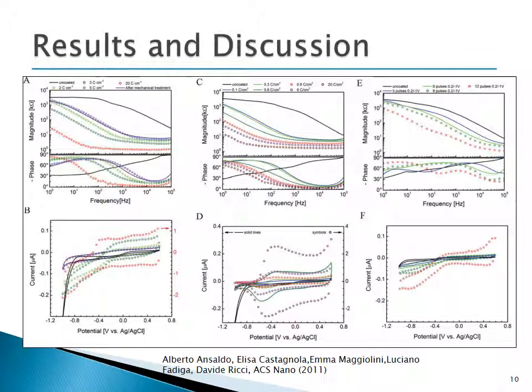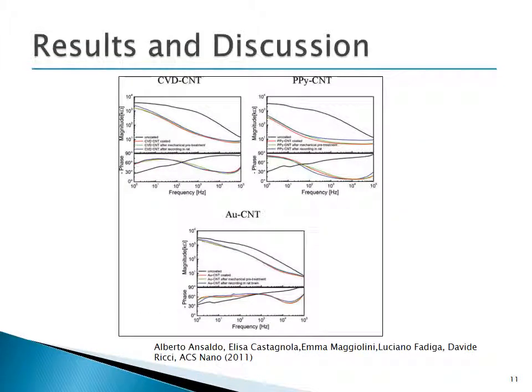Now the results. Here in these graphics, we can see that the black line corresponds to the uncoated electrode, and the other line is the coated one. Polypyrrole and carbon nanotubes was proven to be the electrode with the higher charge injection limit, and also the one that has the best electrochemical performance. To test the electrodes under stress, mechanical strength tests were made.